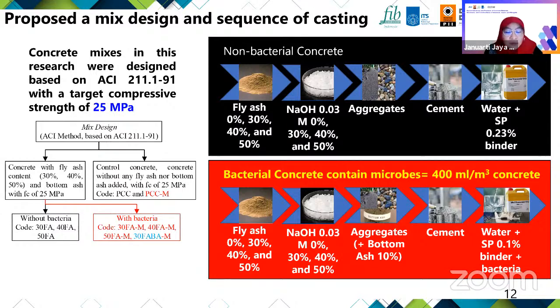We place fly ash first, then mix with the sodium hydroxide, and then continue with all aggregates, followed by cement and superplasticizer, and also add water containing superplasticizer in the final mixture, and also we put in the bacteria. And also we use a different superplasticizer dosage between the black and the red here. Black is the non-bacterial concrete, and the red here contains bacteria, because we keep the bacteria inside the concrete.